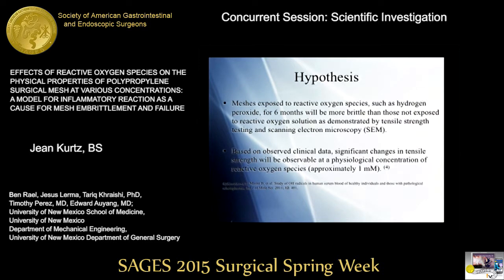So the hypothesis for this experiment was to test this in a laboratory setting. So what we did is we obtained polypropylene surgical meshes. We exposed them to hydrogen peroxide solutions at various concentrations for 6 months. Those concentrations were 1 molar, 0.1 molar, and 1 millimolar. And we tested their change in tensile strength using load displacement testing. And we did scanning electron microscopy to look at the surface of this material for changes.